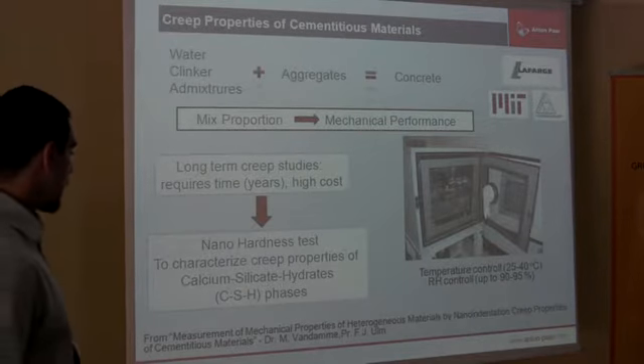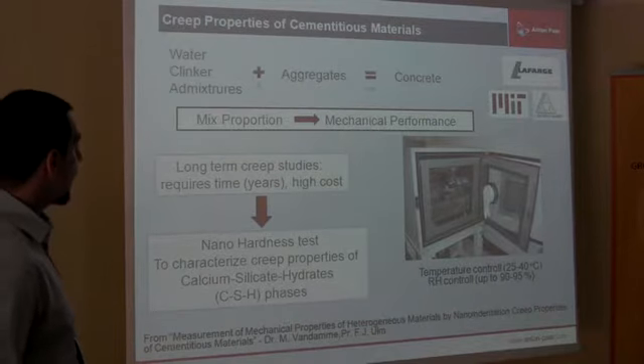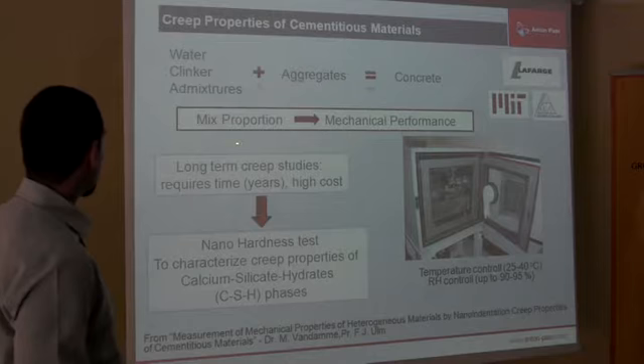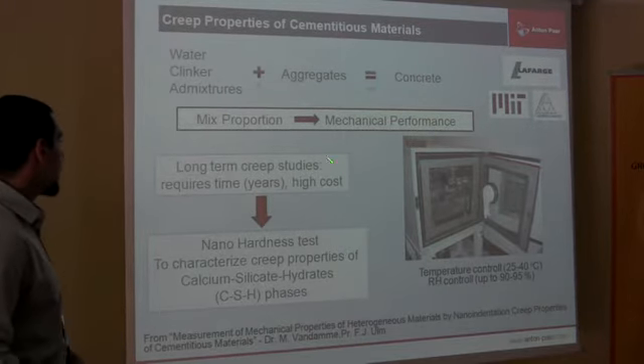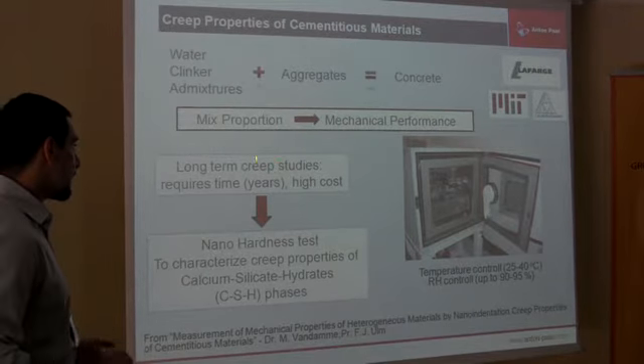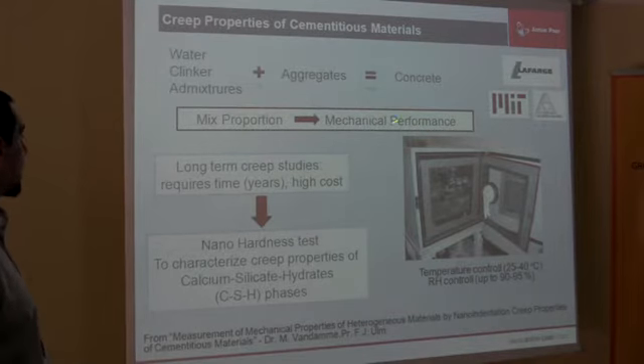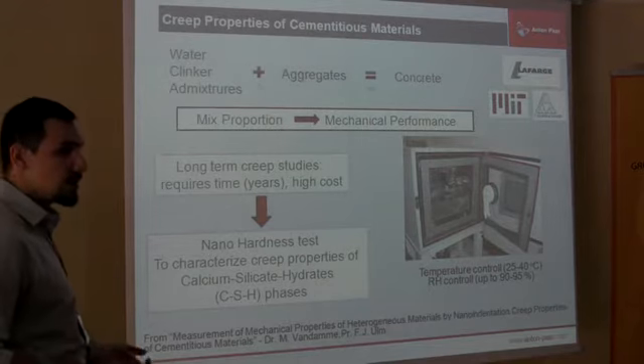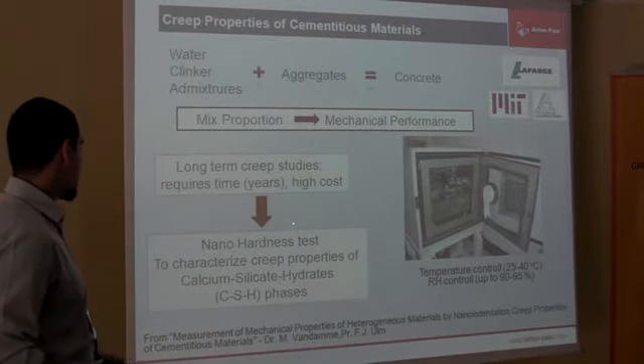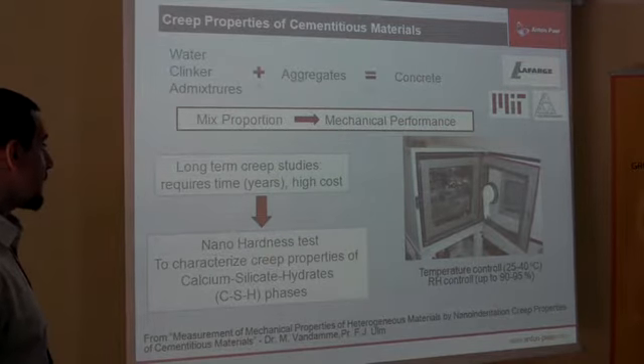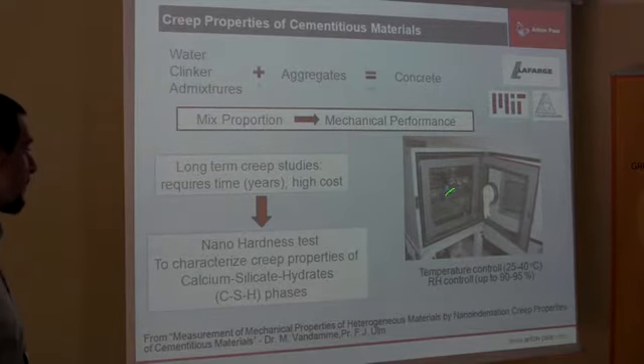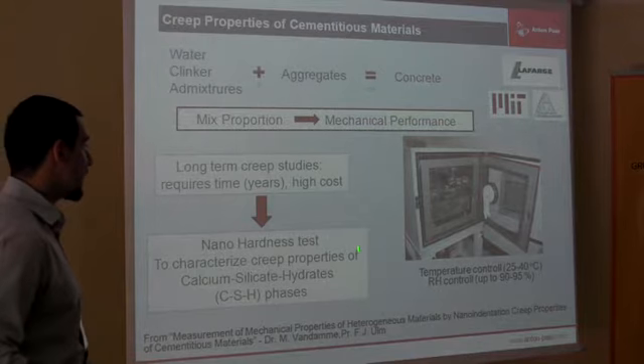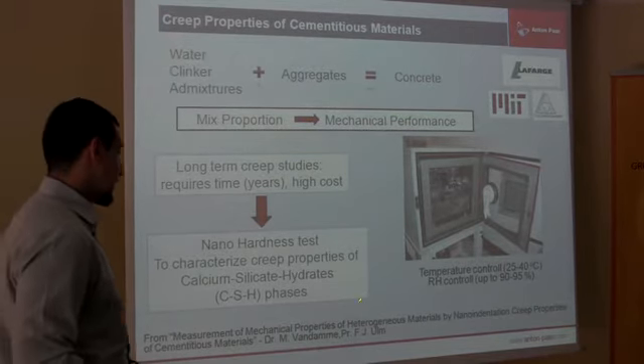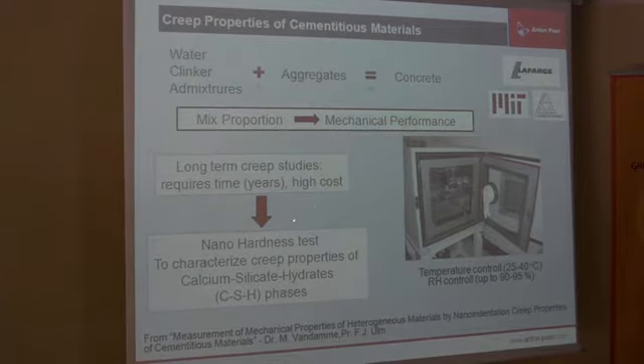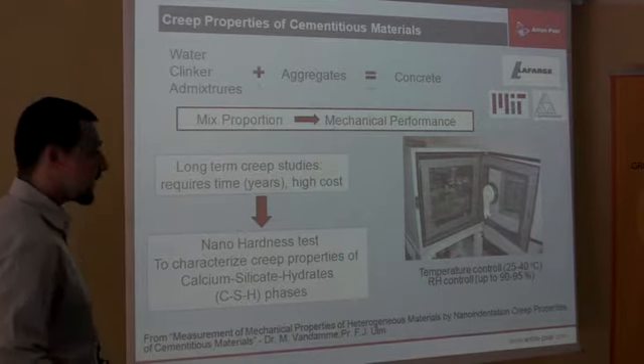Another work also done with Professor Ulm is on concrete and is about creep. The concrete is a mixture of water, clinker, and aggregates, and the mixture proportion is linked with the mechanical performance. To test the mechanical performance, we require time, sometimes years, and the tests are highly costly. With a nano-hardness test in our chamber with temperature control and relative humidity control, it will permit you to test the concrete in different temperature and relative humidity ambiences. We can do the test on the calcium silicate hydrate phases that are strictly connected with the macro creep.